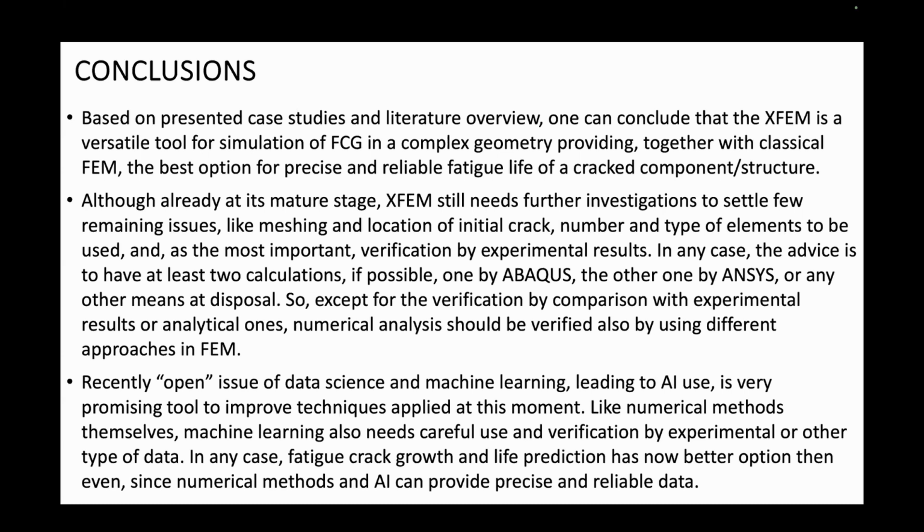XFEM is now in kind of a mature state. We know really a lot about it, but still remaining issues like meshing and location of initial crack, number and type of elements are to be still considered. And of course, the most important, which we lack from time to time, is verification with experimental results.